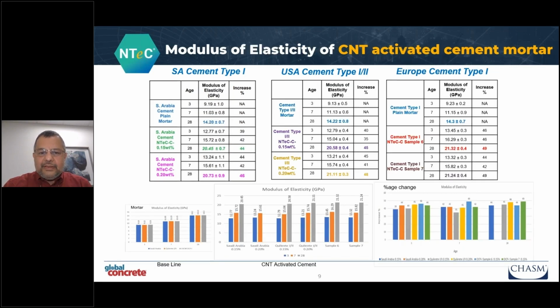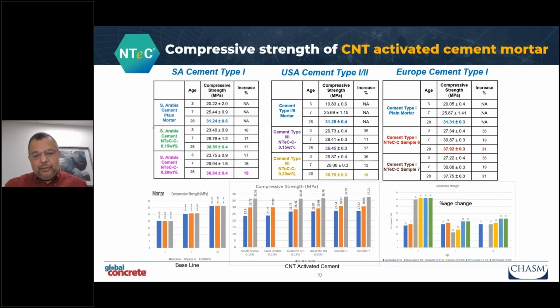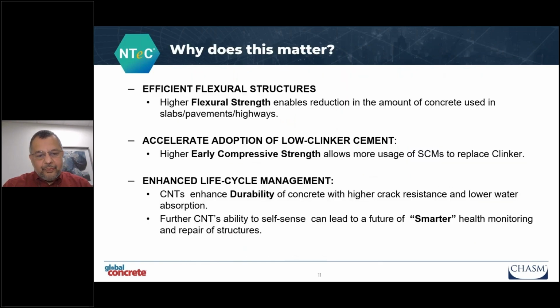And now when you go to stiffness, it goes up considerably, though I'm not too sure how much of this will translate to concrete, but it's a point to be noted. And now we come to compressive strength. You get early compressive strength, at least on two of the three grades, of the order of 35% at the 3-day level. At the 7-day level there will be a still higher gain of early compressive strength, and a late 28-day strength gain of around 15%. So we have a bunch of data. These are some eye charts, but I just want to put it out to show that we are not just claiming; there is deep data behind it, with hundreds of tests done in the background.